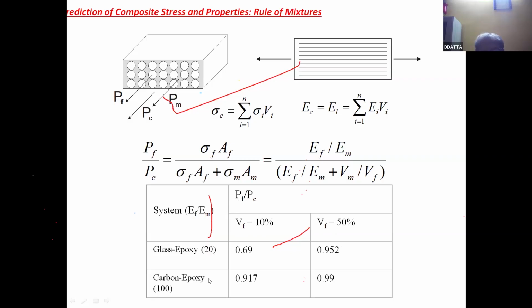And if it is carbon epoxy, then its E_f, the carbon fiber Young's modulus, is very high. It is 100 times more than the epoxy Young's modulus. In that case, even with 10%, 91.7% of the load is shared by the fiber. And if it is 50% volume fraction, then 99% of the load is shared by the fiber. So fiber is the main load carrying agent, and the role of the matrix is to bind the fibers and keep them intact.